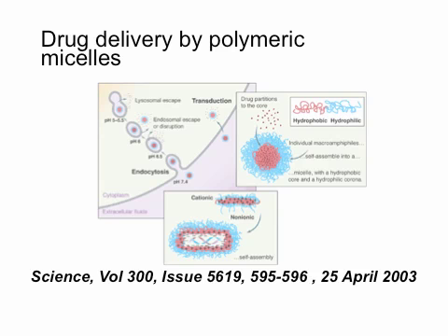And it's a big problem because of shelf life stability. If you make a medicinal compound or a personal care compound, personal care products need 2 to 3 years on the shelf, and for drug delivery purposes, a few months. And this happens in a few days. So that wouldn't be practical, and you need to come up with a solution. How could you do that? For example, covalently bind your drug to the hydrophobic part and then use some clever chemical reaction to unlock it so that it can be released only when it has to be released.